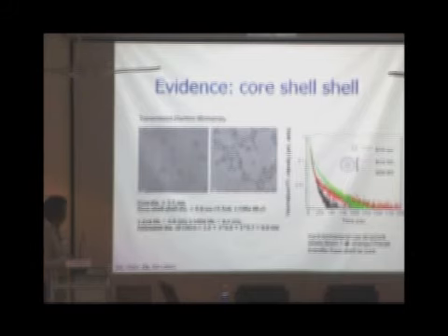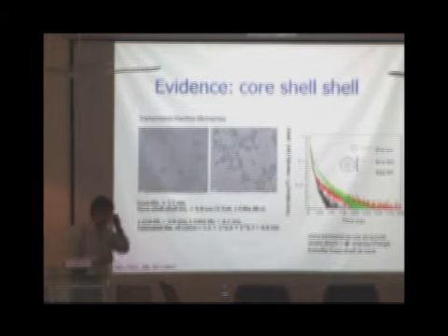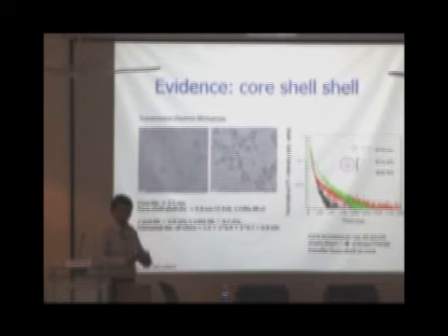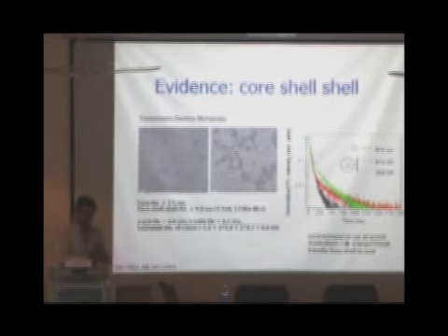But you can calculate the size from the core shell structures, get all the numbers. And what you get from your calculation is 6 nanometers and 5.8 nanometers from what you get from this TEM image. There's energy transfer from the shell to the core materials that clearly shows that these two are definitely connected together and they are not floating apart. They are not two. The main question that comes is, are these two separate particles or are these connected together?